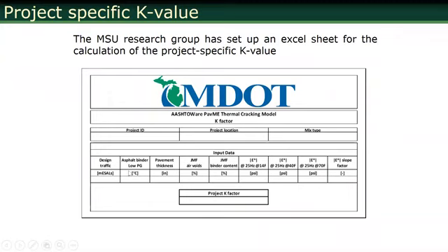You enter the mix design traffic, binder low PG, the layer thickness that you are thinking of, job mix formula, expected air voids, design air voids, usually 4%, sometimes 3.5%, expected binder content, and E star value. These are inputs to the ME anyway. You just take these numbers from that data, K is calculated, and that's the K that you use.